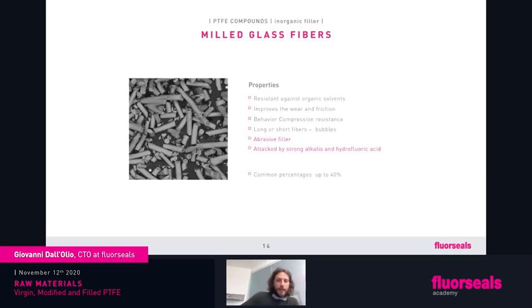Glass fibers. We can have different forms of glass fiber: long fibers, short fibers, also bubbles. The glass is probably, together with the carbon, the most used filler for PTFE, but why? Because this is true mainly for all the PTFE compounds, but let's see it one by one. Glass really improves the wear behavior. Another weak point of PTFE is the wear. So if we have a dynamic application using just regular virgin PTFE, it will wear really fast.